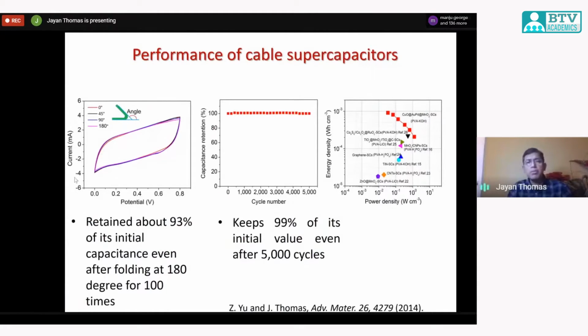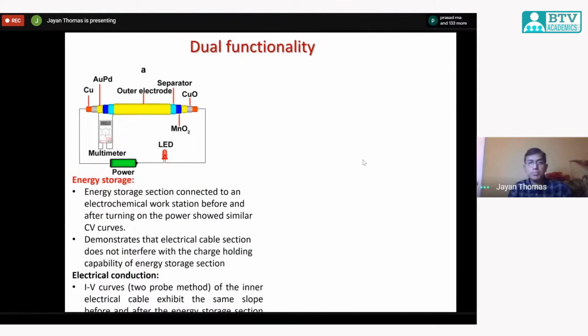So here is the cable, the performance. If you bend it to different angles, you can still see that it retains a very high capacitance, and even after 5,000 cycles, it retains about 99% of its capacitance. And this is a Ragone plot which shows the energy density versus power density compared to other similar devices, and this is our device, which gives a really good performance.